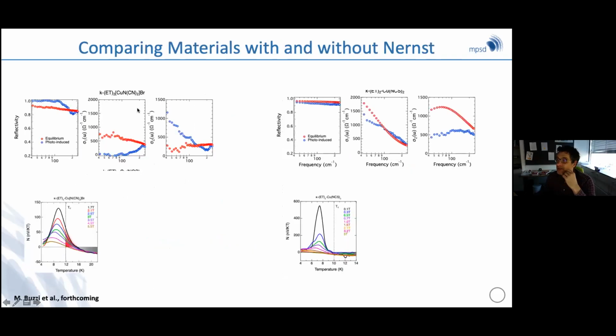So that's basically what I wanted to tell you. If you take the version of the material that has the Nernst effect, we see this light-induced state, whereas the versions of the material that do not have the Nernst effect do not show this light-induced state. So at the moment, we are pursuing this qualitative intuition that light-induced superconductivity is some form of manipulation of a fluctuating state at high temperature that has some features of the superconducting state. And also what I discussed before about the lifetime of the light-induced state of C60 being determined by the nucleation of phase slips and vortices, or as a phase randomization type of relaxation, is perhaps coherent or in line with these ideas.